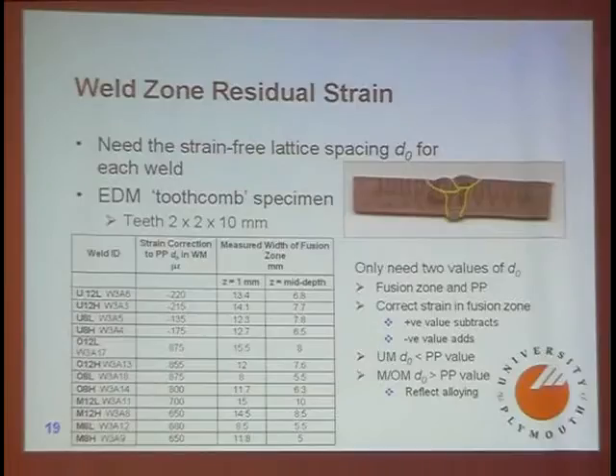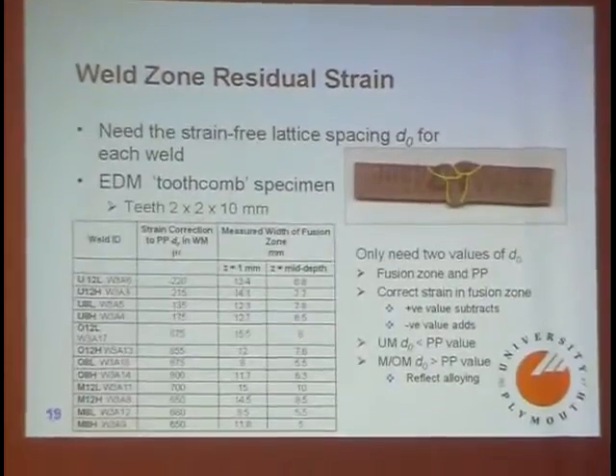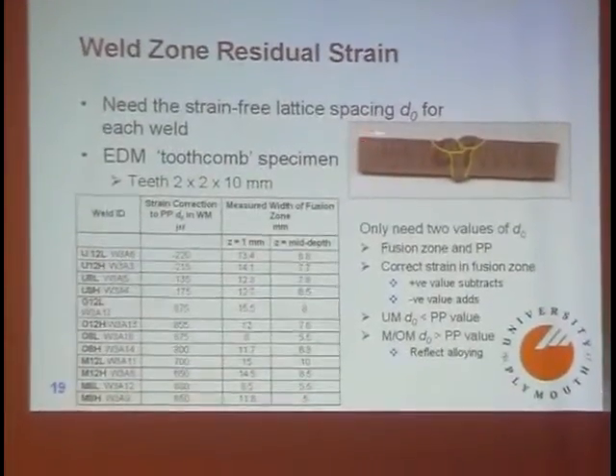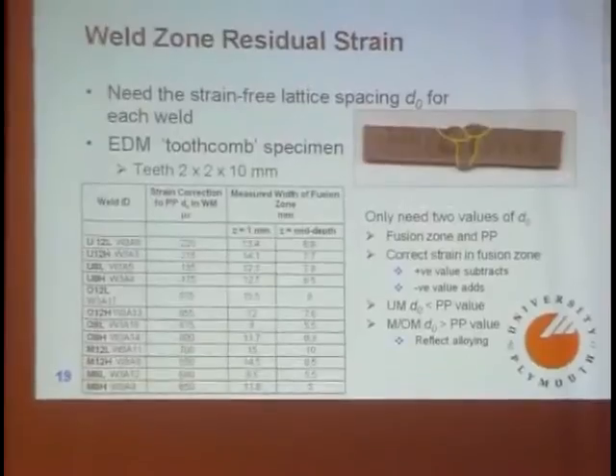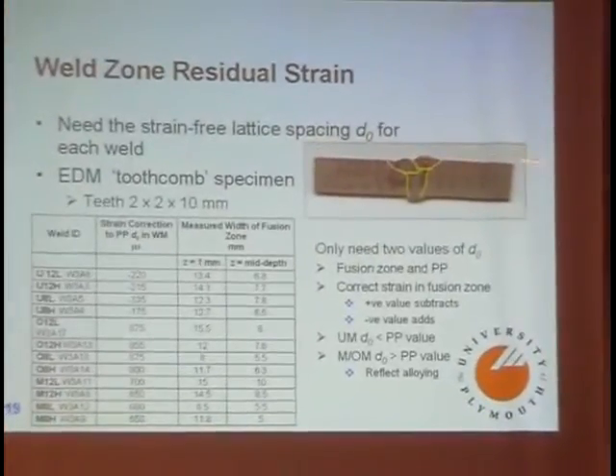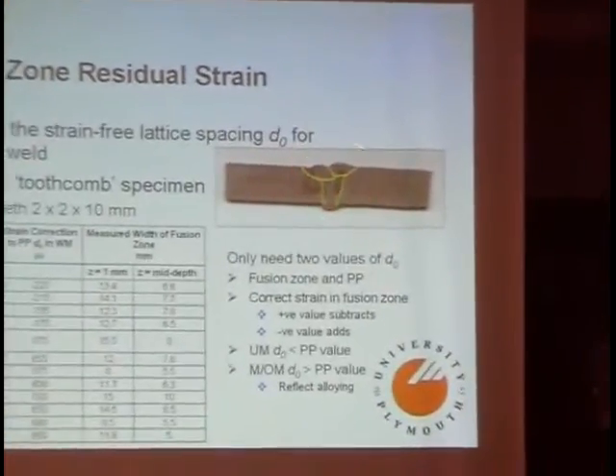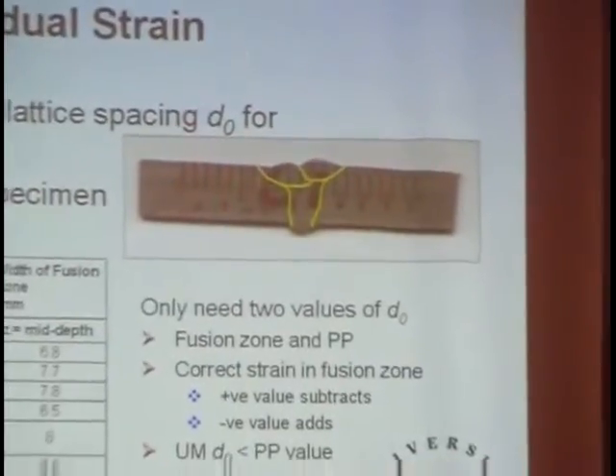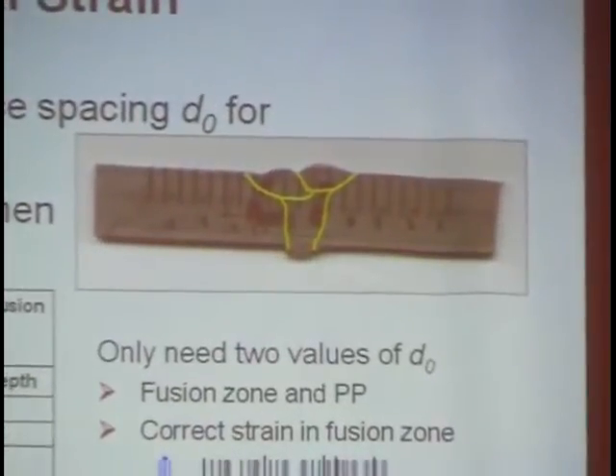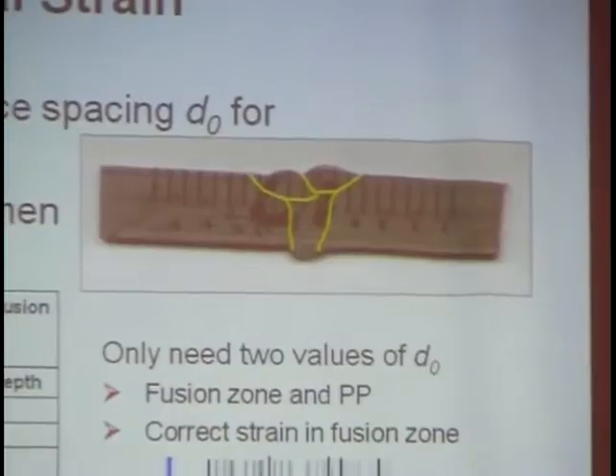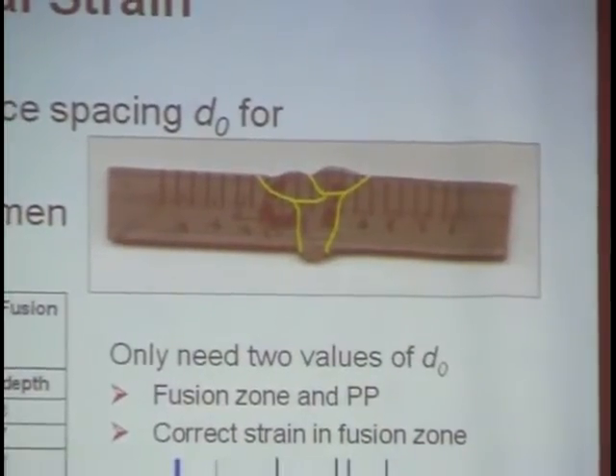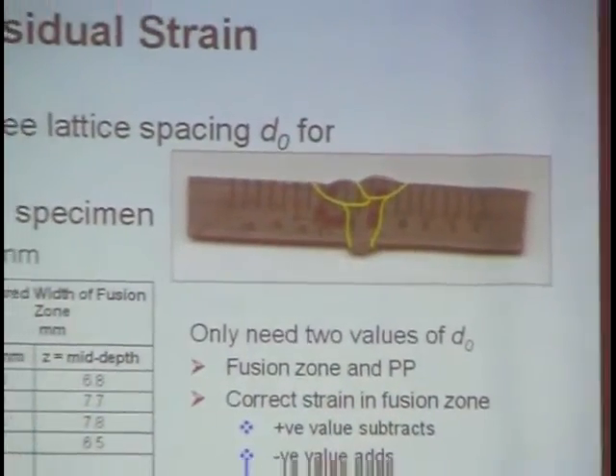Now you have a problem when you make neutron diffraction residual strain measurements. You need to know the lattice spacing of the unstrained lattice. And that's not so simple to do. But one way that sort of works is you can cut a little section off. This is a 2 millimeter thick slice across one of the welds. And one of the things to note here, by the way, is these welds are made by CORUS in the laboratory, and they actually have a very poor profile. But in fact, this is quite indicative of reality.